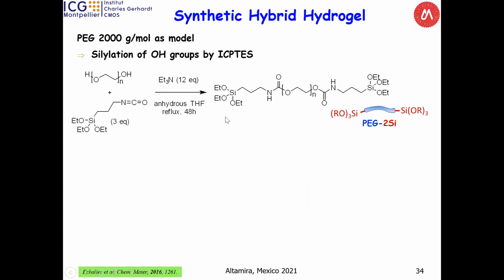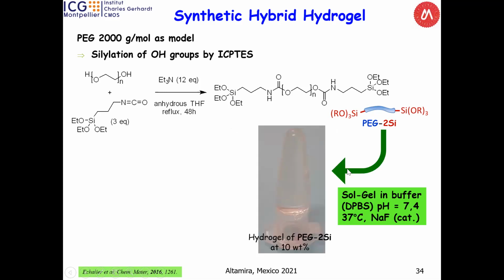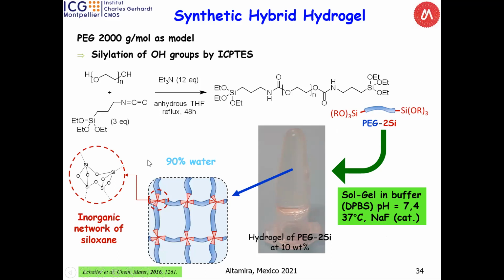It's silylated 2 times. And what happens if we put it in PBS and sodium fluoride? At 10%, 90% of water, the gelation takes place after a few hours, and you get your hydrogel. Your hydrogel contains 90% of water, and as I mentioned before, thanks to the Si-O-Si bond, this inorganic part is here. You have the polymer and Si-O-Si, Si-O-Si.